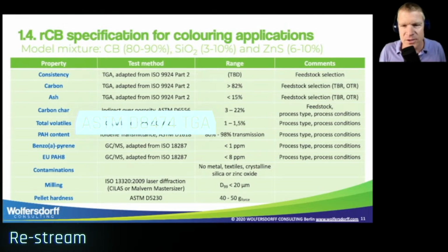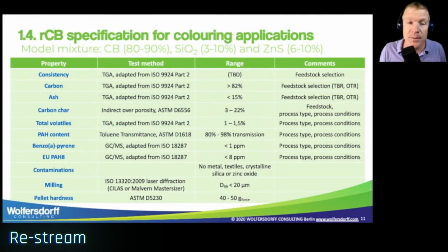The total volatiles should be 1 to 1.5%, meaning this should be moisture only, not organic volatiles. In turn, the PAH content as measured by the toluene transmittance ASTM D1618 should be between 80 and 98% transmission. This is depending on the process type, but also on the process conditions. If we have a result like that in the toluene transmittance, we can chemically test for benzo[a]pyrene, which is the most nasty compound of PAH. We can test by gas chromatography and mass spectroscopy, for example, with an ISO 18287. What we want is less than 1 ppm benzo[a]pyrene. Also, the group of the 8 most common PAH compounds with the same method should be below 8 ppm.